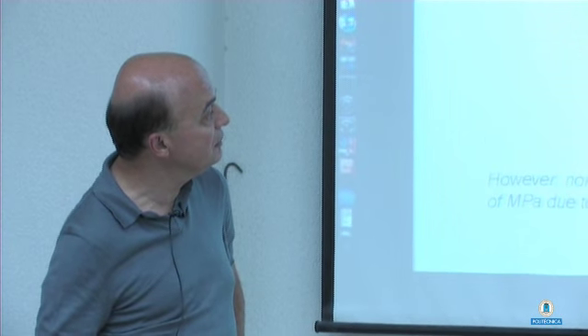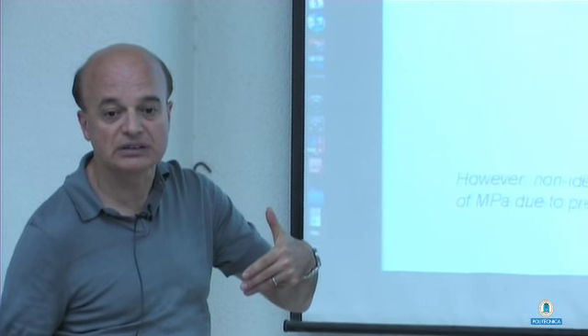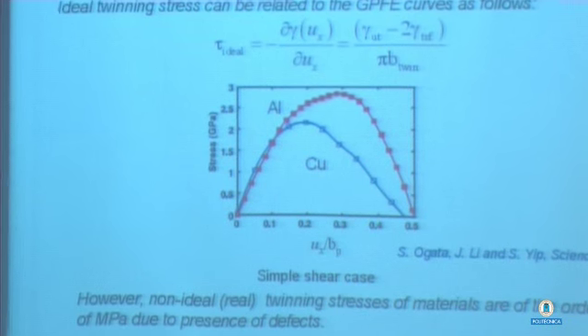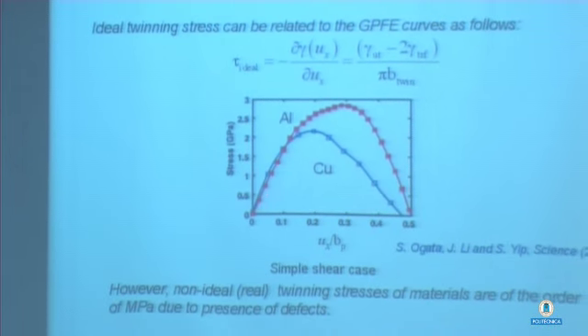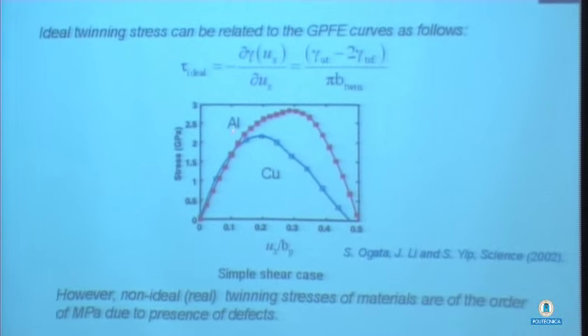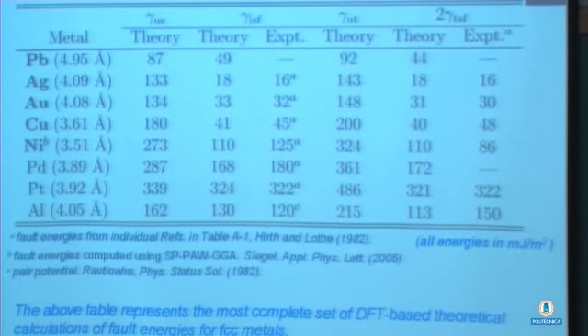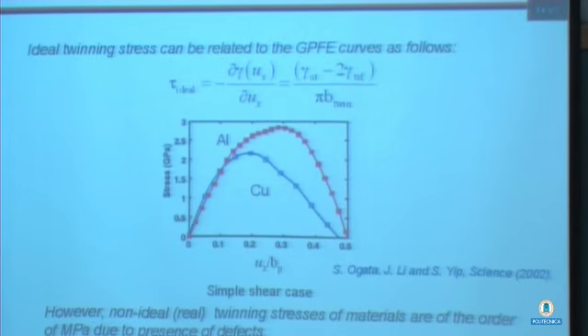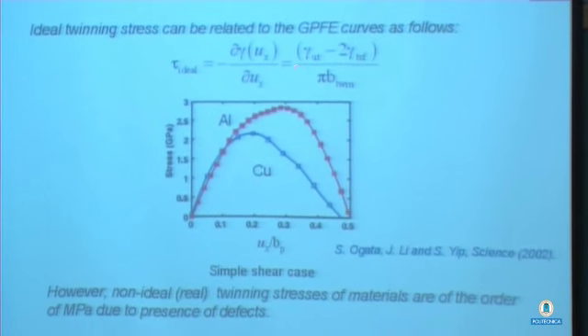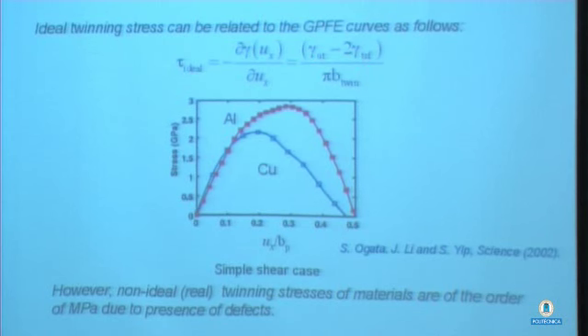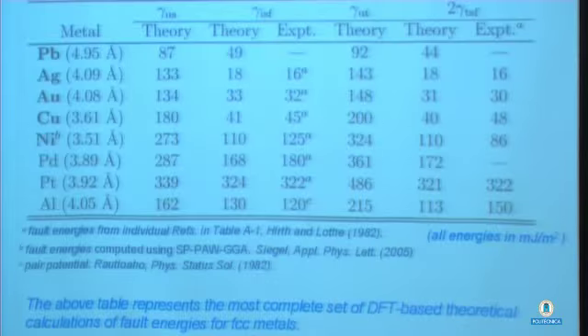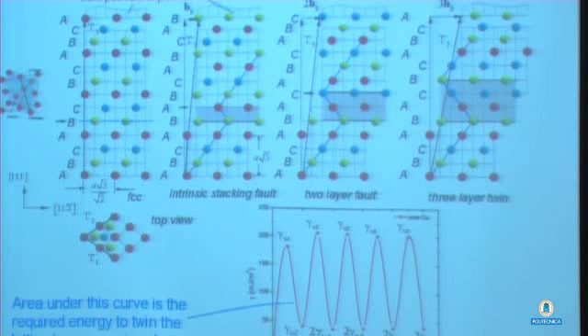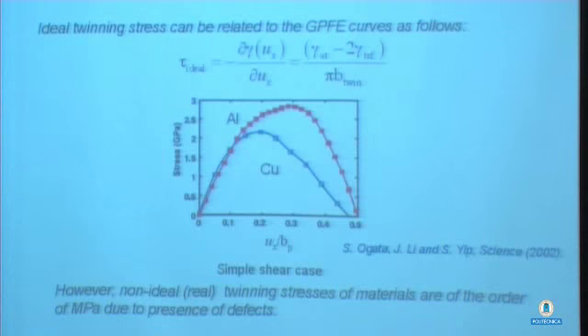what has been done is by taking some of these gamma curves, you take the derivative of these gamma curves, and you can try to predict stresses, for example, for slipping or twinning. But that gives you very large stresses. So you take the energy curves, take the derivative of these, or you calculate ideal shear stresses, (gamma UT minus 2 gamma TSF) divided by pi b twin. b twin is this value here, okay? The characteristic length of the material. These ideal stresses would be very large for aluminum and copper, and that's done by Ogata and Yip.